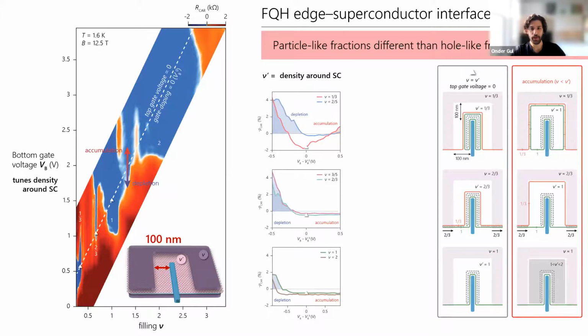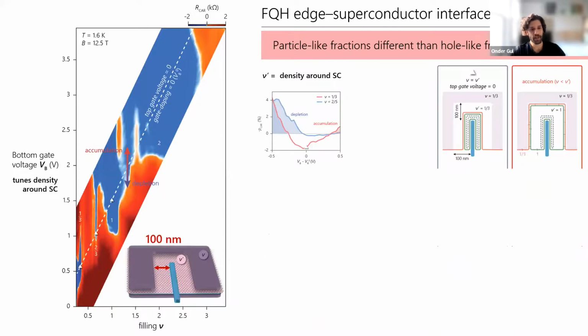This situation is different for the case of particle-like 1/3 filling. Here, the incoming charges are carried by the fractional edge. These details may hold a clue as to why particle-like fractions are different than the rest of the fillings, but also maybe reveal other interesting features. For example, if we compare the edge state configuration for the neutral and the accumulation regimes of 1/3, and also consider the observed suppression of CAR in the accumulated regime, it could suggest that the residual edges are fully proximity gapped and maybe can be seen as part of the superconductor. Basically, the lack of a signal in the accumulation regime suggests that the equilibration between 1 and 1/3 is incomplete, but then the situation is similar in the neutral case, for which there is a CAR signal.